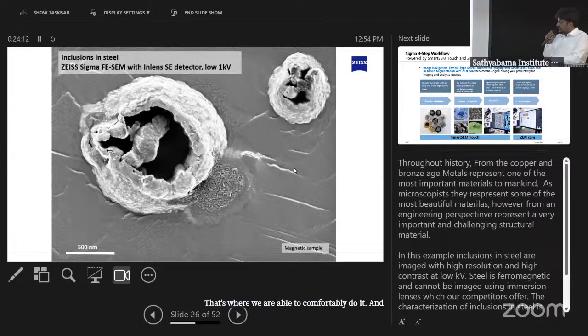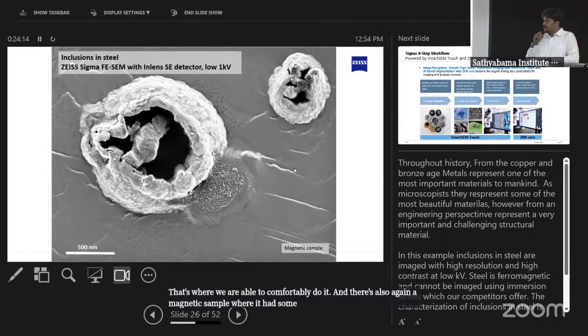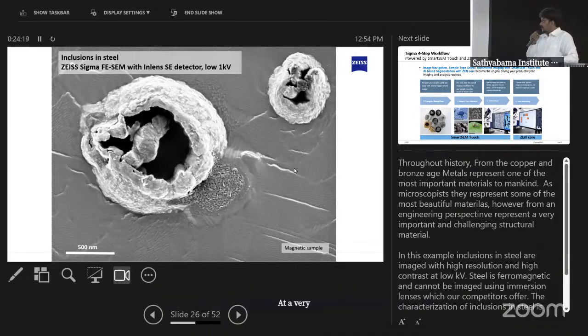And this is also again a magnetic sample where it had some inclusions. We were very clearly able to capture it at a very low kV imaging as well.